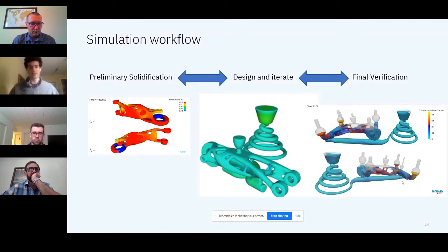So once we saw this, we then started messing around with using these spherical risers that we could only really place using 3D sand printing, and also moving our sprue location so that we would get even filling throughout the whole casting. And so finally, on the right here, this design is where we placed numerous risers in our problem areas. And then also we had the sprue on the one end with that long runner so that we could facilitate even filling throughout the entire filling process. And so next slide, please.